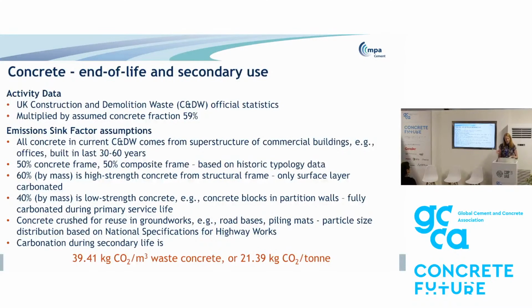To calculate this for a UK specific factor, we took UK construction and demolition waste statistics. We found that the concrete fraction is around about 59%. We then worked out how much of that waste was from what type of concrete, so we could work out the strength and therefore work out how fully it would have carbonated, etc. And we came up with this result of 39.41 kilograms of CO2 per metre cubed of waste concrete for the emission factor, which equates to 21.39 kilograms of CO2 per tonne of concrete.